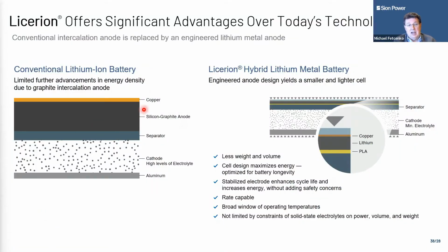You start out by saying in a conventional lithium ion, graphite is the anode, and that's obvious. And almost everybody uses a little bit of silicon. There's a lot of companies touting the idea of using a lot more silicon or even pure silicon. There are issues with silicon with cycle life, with energy, with expansion, and everybody's got their own ideas. What Sion is doing is taking the graphite out. We scrap the graphite anode and replace it with a metallic lithium anode. Now that can be a foil, but what we're actually doing is something thinner than a foil. We're using a vapor deposited lithium film as the anode. You think about a 5 micron or 10 micron lithium metal anode.